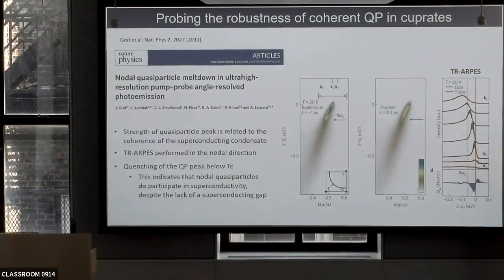Both of them, I would expect, should change equally if I, for instance, change my condition for photoemission in some way. So if I change polarization, for instance, I would expect both of them to scale down equally because they are related to the same original excitation. What you can see here is something happens to the coherent part, which is not apparently tracked by the incoherent. So there was no renormalization.